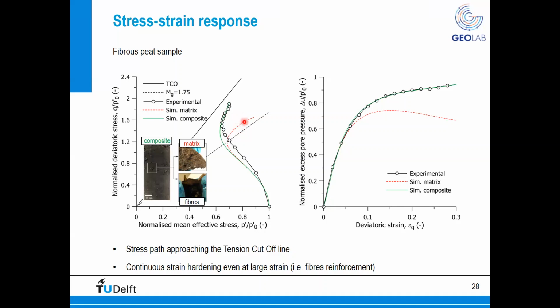So even though the matrix is already at failure, due to the additional confinement of the fibers, the overall impression that you get from laboratory tests is that this material is much stronger. And this is true both in terms of the deviatoric stress response that you can see here on the left-hand side, but also, and more importantly, in terms of pore water pressure. So you have an additional increase in pore water pressure compared to the matrix due to this additional confinement of the fibers.